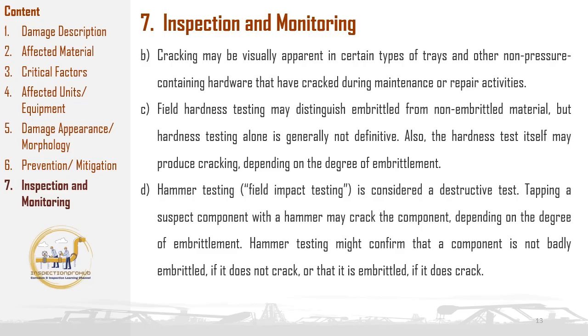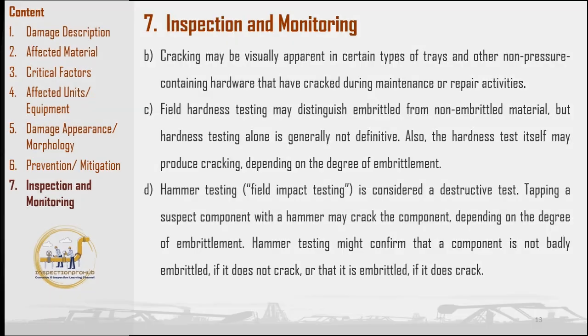Hammer testing, also known as field impact testing, is considered a destructive test and should be approached with caution. This method involves tapping a suspect component with a hammer, which may cause cracking depending on the degree of embrittlement. While hammer testing can confirm that a component is not severely embrittled if it doesn't crack, or that it is embrittled if it does crack, it carries the risk of damaging the component being tested. This technique should only be used when the potential for component damage is acceptable and other non-destructive methods have been exhausted.